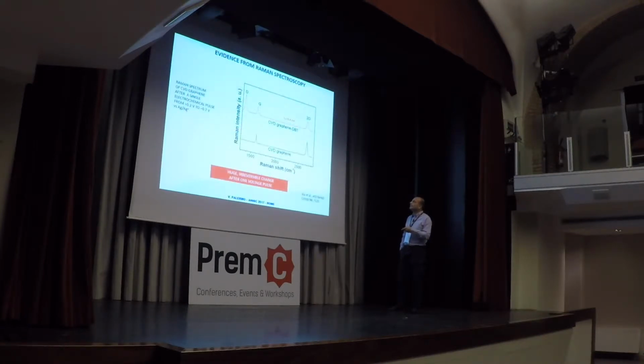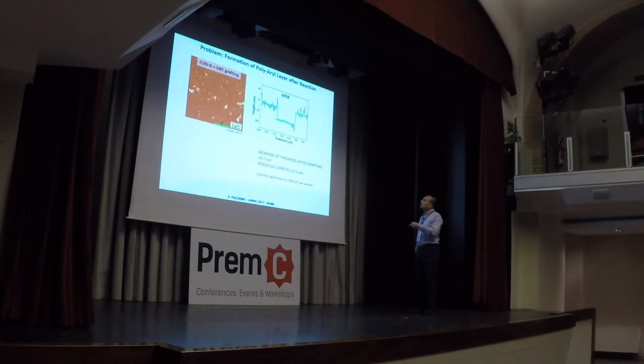I'm not going to go into details on this, but looking at the thickness, the situation is not as ideal as we show here, because we see that much more material is deposited on the surface. I will not go into details on how we demonstrate this, but the problem is that these kinds of radicals become so reactive that you have multilayers and a disordered layer. That's why we decided to combine supramolecular chemistry and covalent chemistry to improve our control of this.